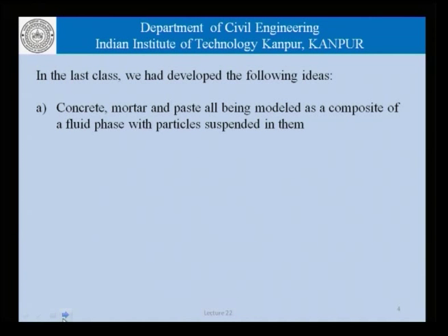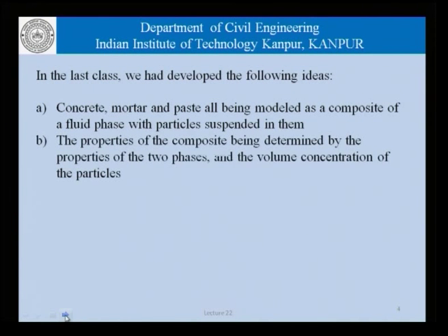Concrete, mortar and paste all can be modeled as a composite having a fluid phase with particles suspended in them. Paste can be modeled as cement particles suspended in water. Mortar can be modeled as sand particles suspended in paste, and concrete can be modeled as coarse aggregate suspended in mortar. The properties of the composite, whether it is paste or mortar or concrete, can be determined by the properties of these two phases.